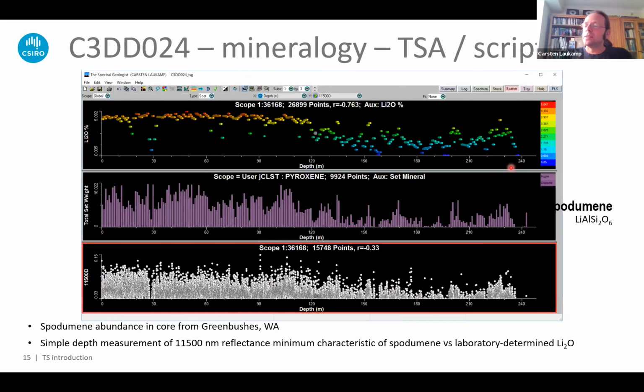You can look at this also another way. These are all plots generated in the Spectral Geologist software. We can import geochemistry into this drill core data set. And this is the lithium content plotted downhole. We see there's lots of lithium at the top, and it's decreasing a little bit further down. And this coincides with the abundance of pyroxene, in this case spodumene. So we have roughly more spodumene at the top compared to the bottom.